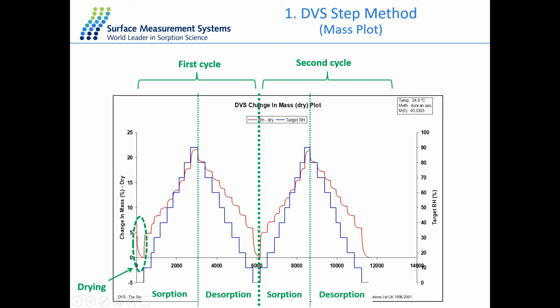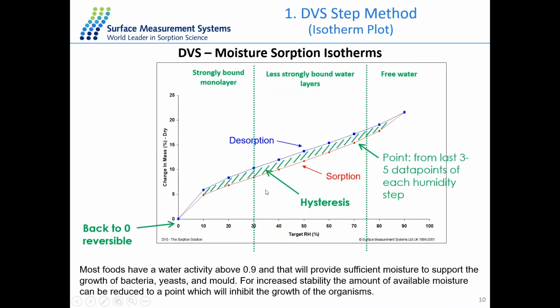And these are the moisture sorption kinetics data from a mass plot, which is the mass change as a function of time. If we take the equilibrium mass uptake and plot it against the target relative humidity, then we can get this moisture sorption isotherm for the experiment. So we have the red line for the sorption branch and the blue line for the desorption branch. And quite a lot of information can be obtained from this isotherm plot.